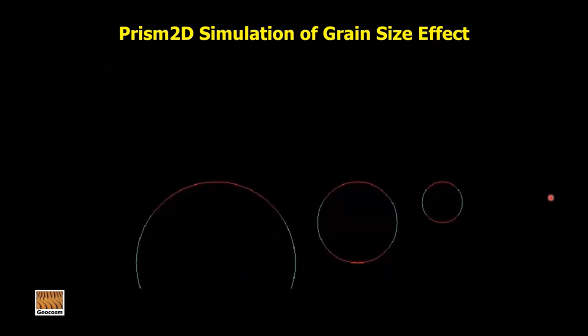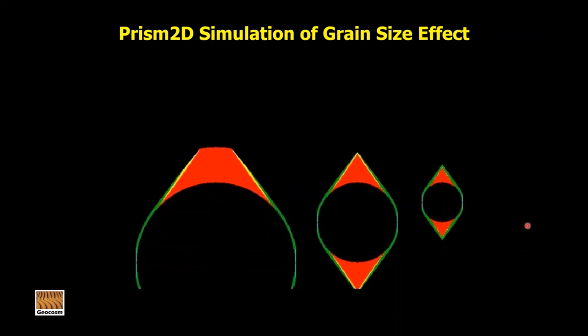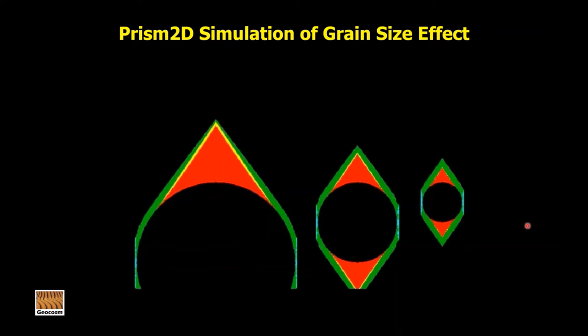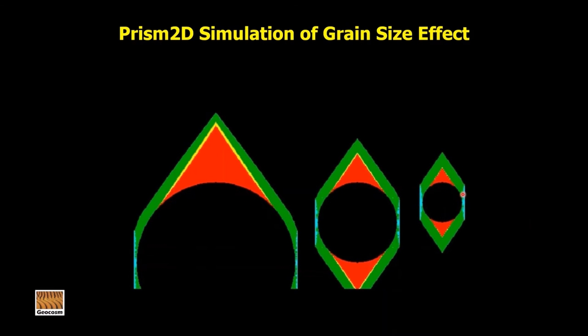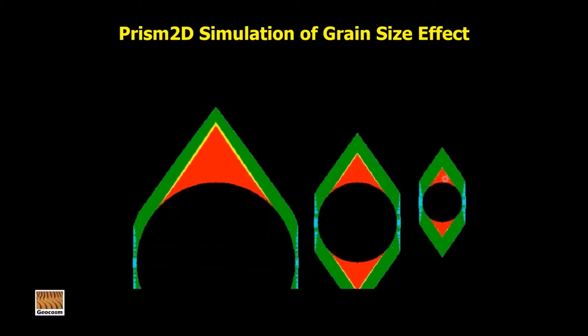And to address that, what we're going to do is look at a simple simulation with our Prism 2D model. These are circular cross-section grains, and I've lined them up so that their top edges are all the same horizontal position, and these guys all have their C crystallographic axes oriented vertically. And so the colors here represent different rates of growth on different types of nucleation surfaces, with the red representing growth on non-euhedral C-axis surfaces, the green on pyramidal faces of the quartz crystal, and the cyan here, which is even slower growing, which would be growth on the prismatic faces of the quartz crystal.